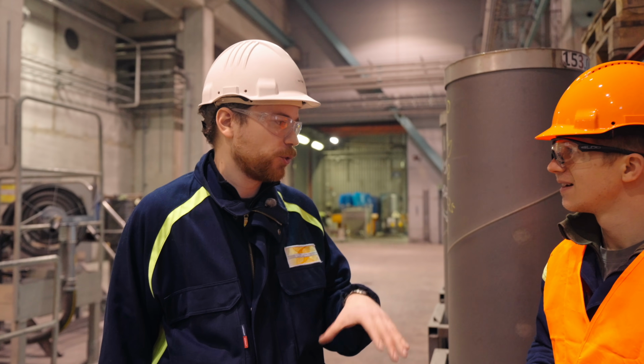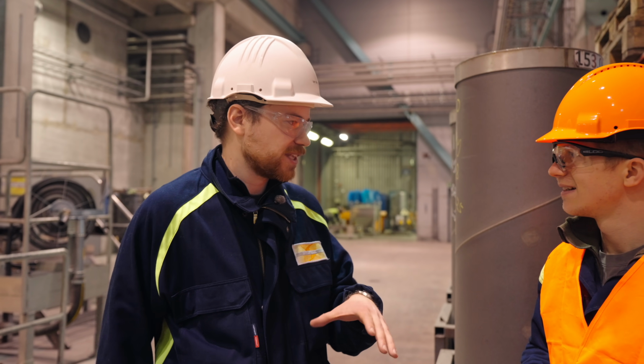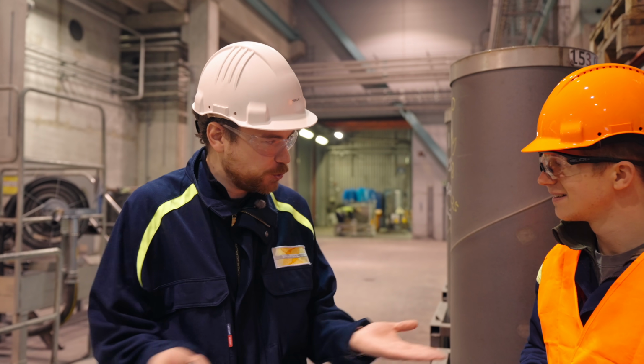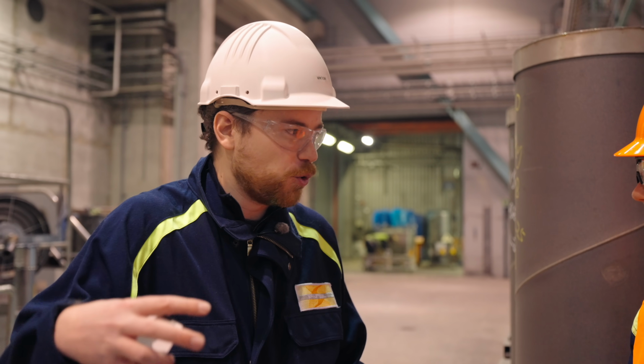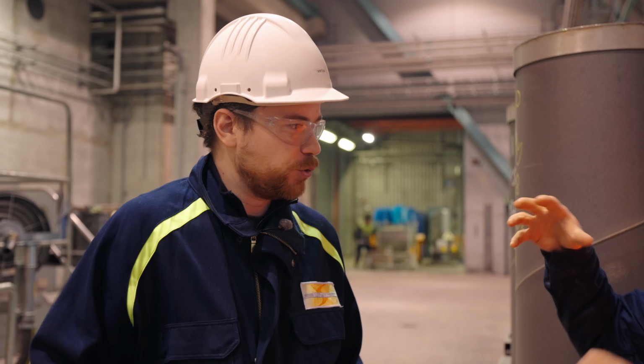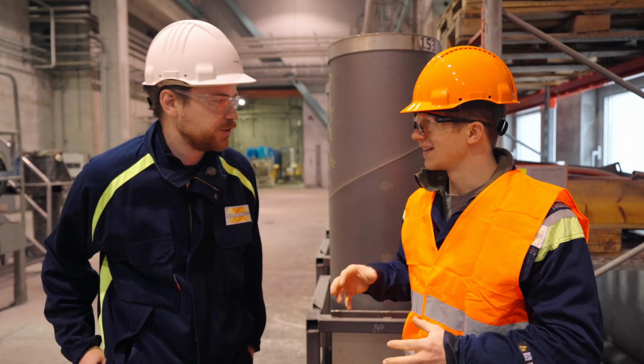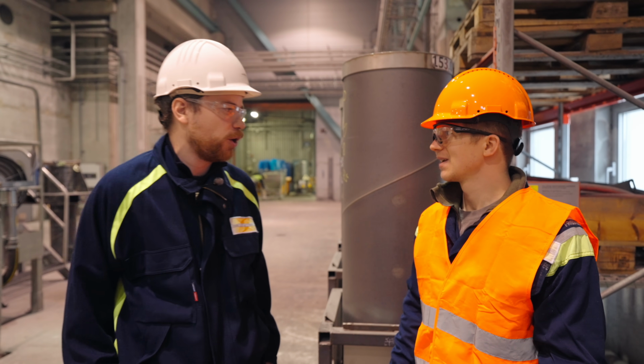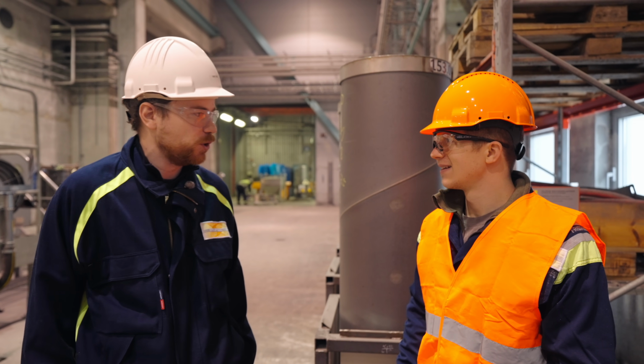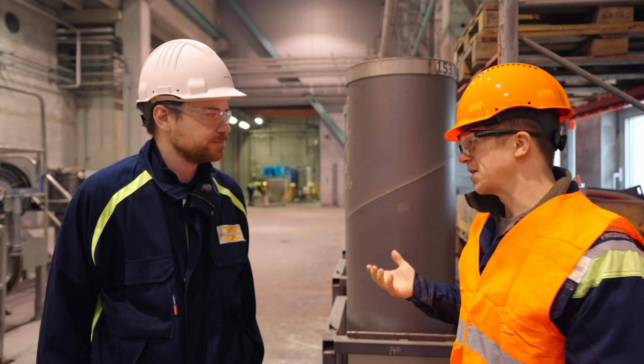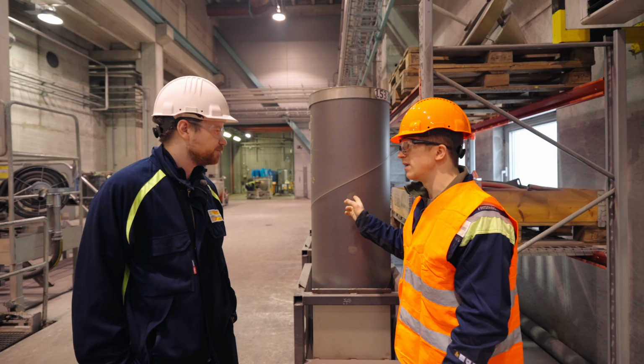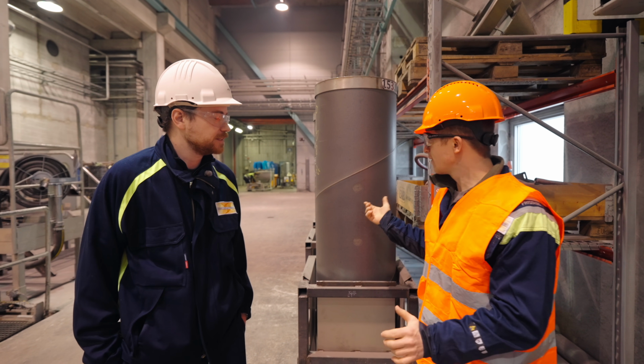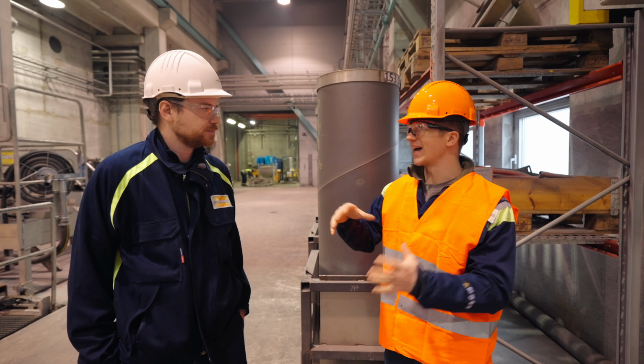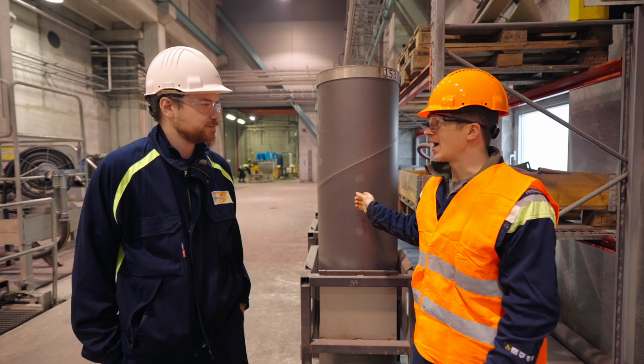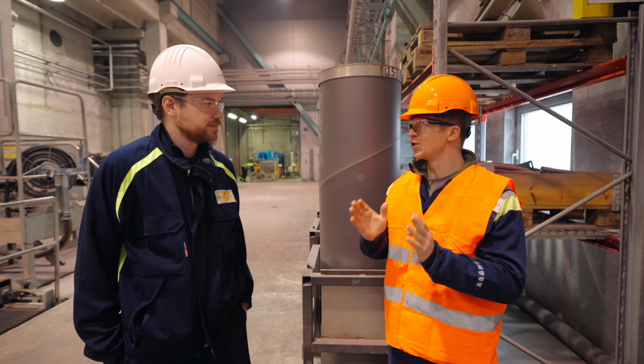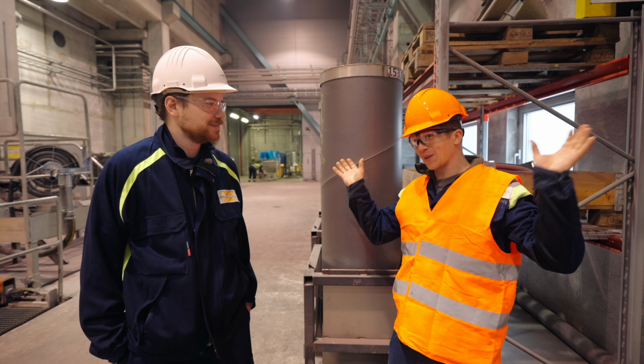So HIP stands for hot isostatic pressing. Isostatic just means that instead of hammering from two sides and then other sides, you're doing all of that pressure equally throughout all directions. Yes, and you do that by applying a high argon pressured gas into a vessel, basically. And what's very interesting about that is this is, you said, a 3 millimeter wall on this pipe. Correct. If that was to be forged under dies, the wall on that pipe would need to be like 100 millimeters for it to just not burst all over the place.